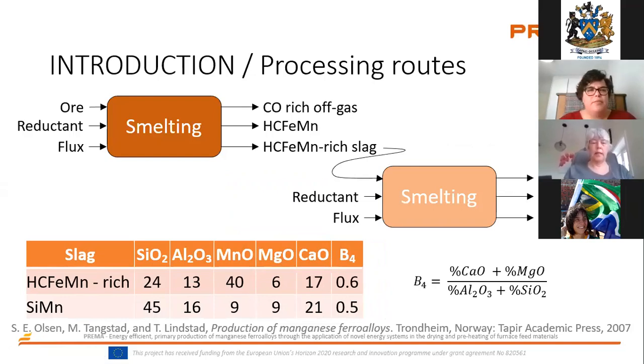What's done in Europe and elsewhere is they follow what they call a duplex route, where they feed ore for the production of high carbon ferromanganese, and produce a slag rich in MnO. Slag composition at the bottom, the MnO of the slag is 40%. They can do that because they have lower basicity ores. They import their ores not only from South Africa, but also from Gabon and from Australia and elsewhere. And Eli can tell you more about that.